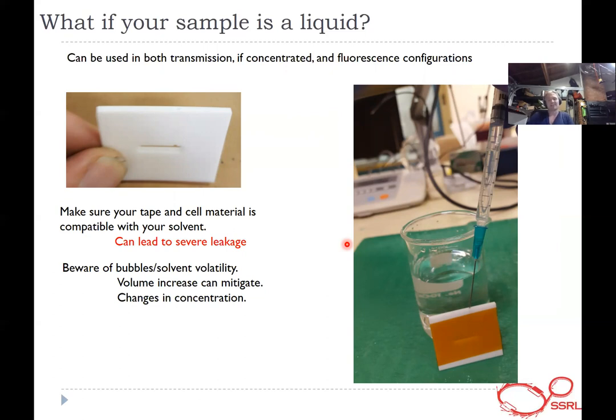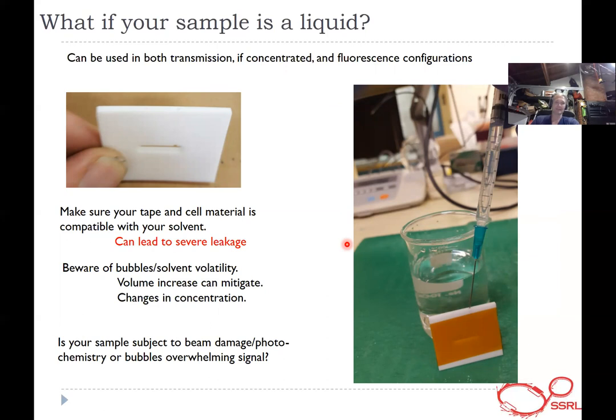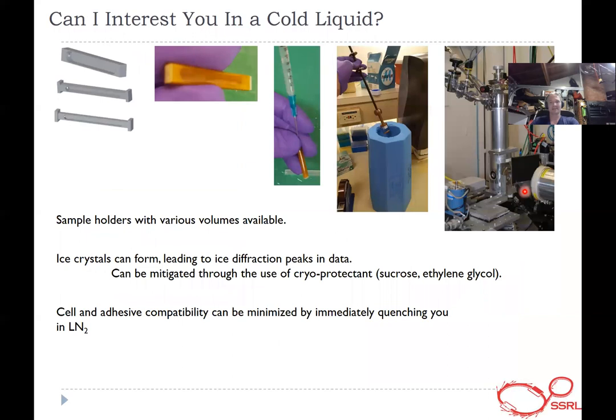Another concern is if in the beam your solvent starts evaporating, you're changing your concentration. We can mitigate that to a certain extent. Bubbles can form. Bubbles will basically create a sample-free void that will make your data useless. So those are things you need to think about. Is your sample subject to beam damage, photochemistry, or bubbles overwhelming the signal? If that is the case, we have another workaround, which is we can freeze them.